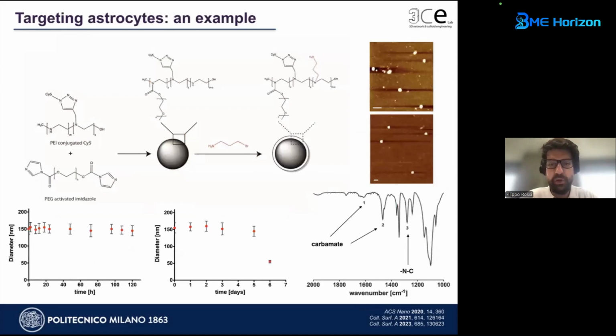What about the coating, even if it's not a real coating? We are talking about very, very, very small. What we did, we performed the same reaction we did before. So we started with PEG, activated with imidazole. We added polyethylenimine, in this case conjugated with CY5, not rhodamine, because generally it's commonly known, and we will see